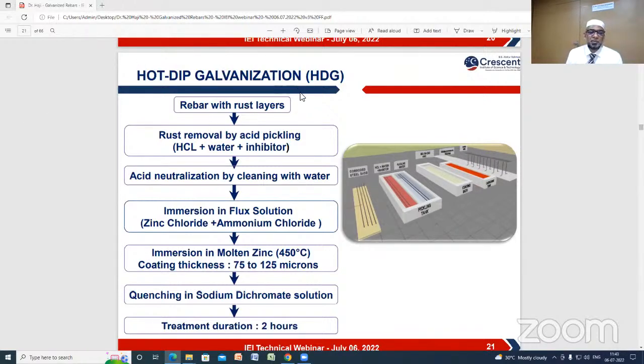So these are the salient steps in hot dip galvanization, in the batch process, in the factory. First, rust removal is done by pickling in acid solution. Then acid neutralization is done by cleaning with water in the second tank. Then a flux solution is applied over this rust-free rebar to improve the adhesion between the rust-free rebar and the zinc. Then it is immersed in molten zinc at a temperature of 450 degrees centigrade. Then quenching in sodium dichromate solution. Don't worry about these process steps. This is as per Indian standards and ISO standards. These are the normal steps they follow in any galvanization unit.